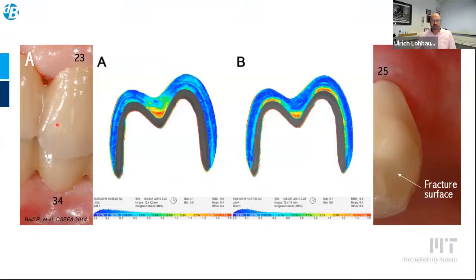This is an example, sorry, that should be animated. So in the background, you see a chipped structure here. This is the visual inspection from the clinical image. So this one is chipped, and this was one thing that happened, let's say 10 years ago, very, very often, when dentistry switched the core material, here's the core material, from metal core materials to zirconia, with a material having a completely different thermal conductivity than metals, and then by veneering in the same way as the metal reinforced crowns, we in the beginning created a lot of residual stress at the interface of such a crown, and that led to a high incidence of chipping off the veneering material.